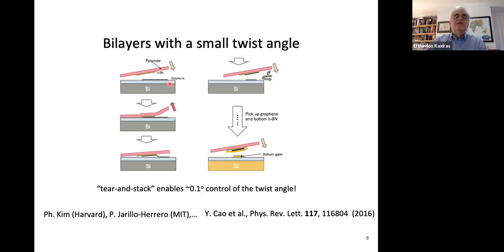So the way they do it is they have, let's say, one layer of a two-dimensional material like graphene. They stick on it a different material like boron nitride, and on half of the graphene, then they lift up this half, so the graphene is torn into two pieces, but now you know exactly the relative orientation of these two pieces, so you twist the top a little bit and deposit back on the bottom, and you have these well oriented with very good control of the twist angle different layers.